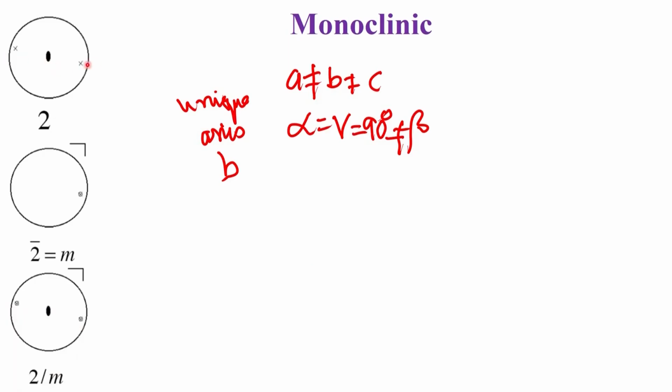The equivalent points are x, y, z, and I want you to figure out what the equivalent point is given the two-fold operation. Obviously, the two-fold operation will keep the identity of the object the same, that means there is no inversion here. So, the value of x will go to minus x, the value of z will go to minus z, because the B axis is unique, there is no change of the y value. So, you will get equivalent points corresponding to the two-fold operation as follows: x, y, z and x bar, y, z bar.